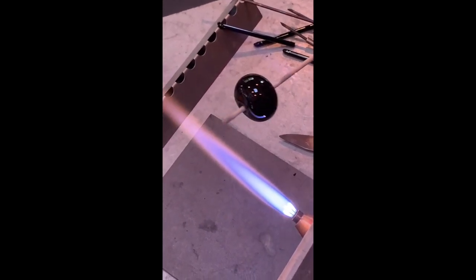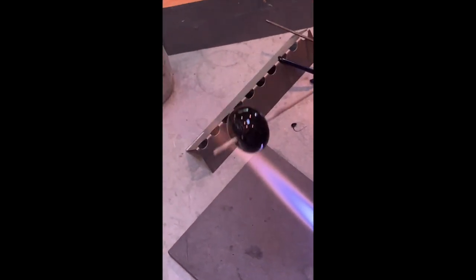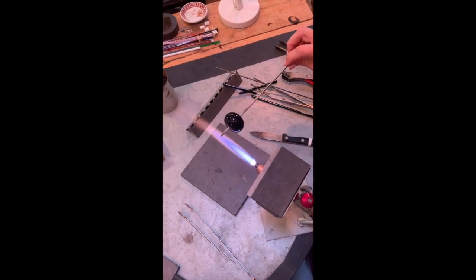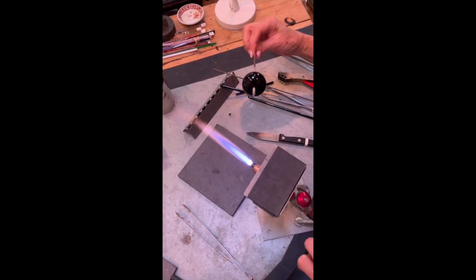What you can look for as you're blowing, essentially, is reading the heat base of the bead to be about the same temperature as when you would pull a twisty or a stringer. You need the glass to be moving, but you don't want it to be soup.